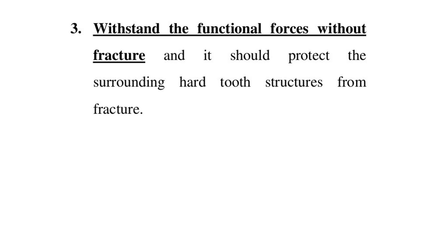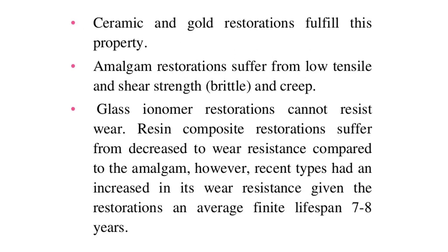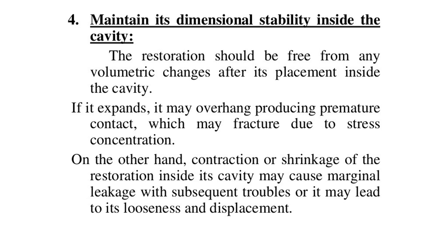Amalgam restorations suffer from low tensile and shear strength, brittleness, and creep. Glass ionomer restorations cannot resist wear. Resin composite restorations have decreased wear resistance compared to amalgam; however, recent types have increased wear resistance, giving restorations an average finite lifespan of 7-8 years. Regarding dimensional stability, the restoration should be free from any volumetric changes after placement. If it expands, it may overhang, producing premature contact, which may fracture due to stress concentration. Contraction or shrinkage inside the cavity may cause marginal leakage or lead to looseness and displacement.